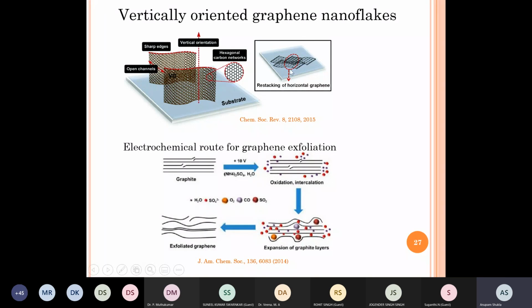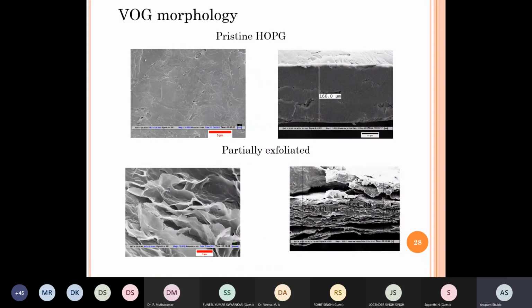So people have done this using CVD, but then there is another approach which is being done, which is to exfoliate the graphite. So your conductive base remains graphite, and then some of the layers of the graphite are kind of peeled partially. So they are peeled partially and moved up. Okay? And if that is done, then they become vertically oriented graphene flakes. So this is something that we tried at our laboratory here.